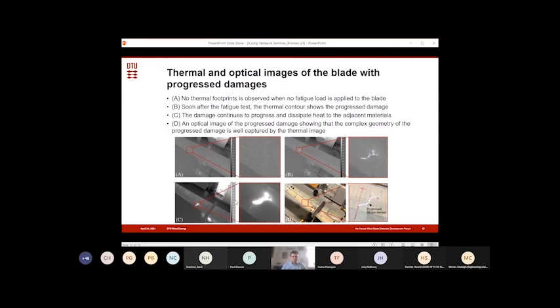Another here where we have made a crack into the trailing edge on purpose, and then a crack is growing from this. So in picture A, the blade is at a standstill. You see nothing. And then shortly after you start with the fatigue test, the cracks show up clearly as a thermal image, and as it starts growing, you will see heat coming more from the direction it grows in, and it's easy to see from quite a big distance with a thermal camera. So it's easy to employ in drone applications, and with the naked eye, it's not easy to see it.